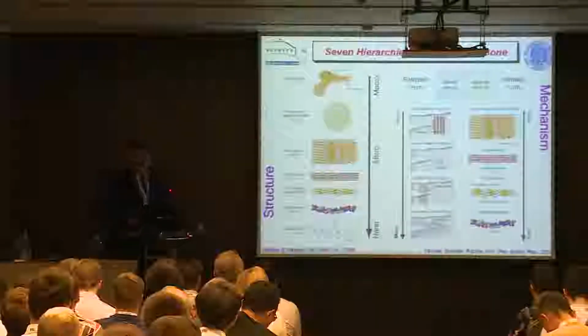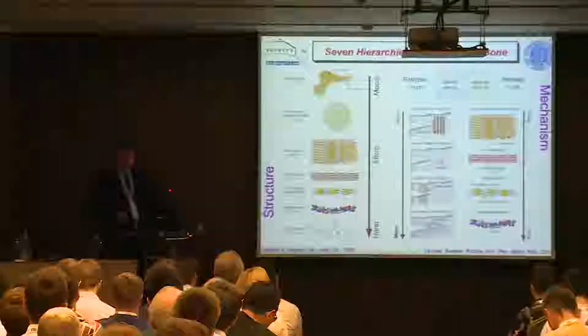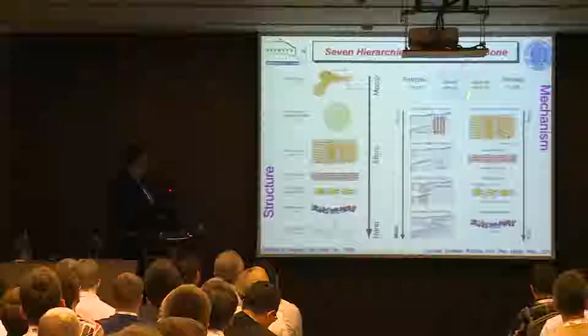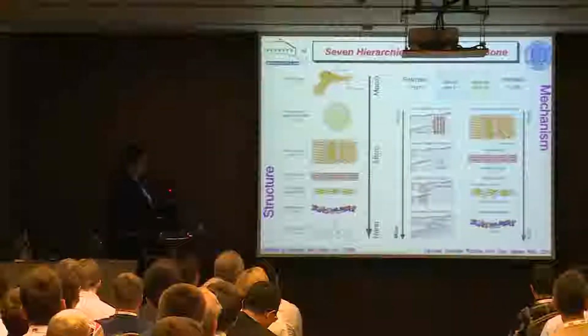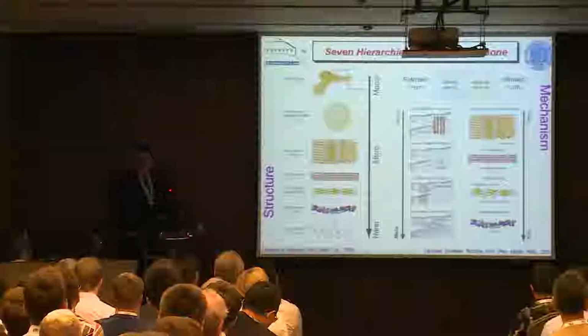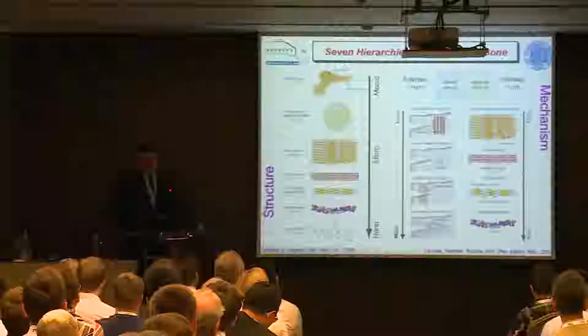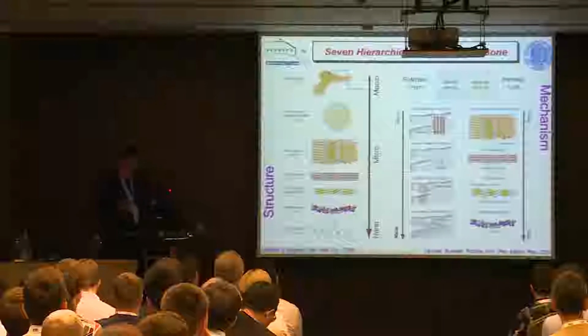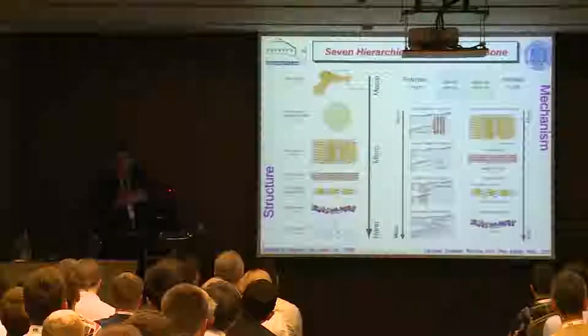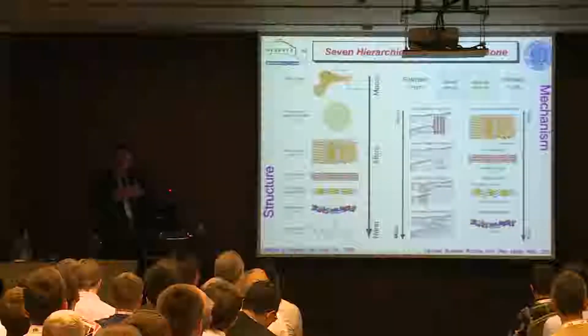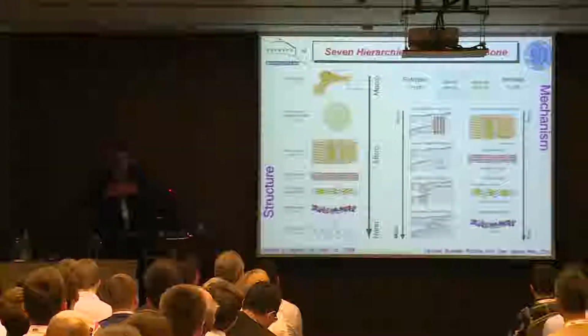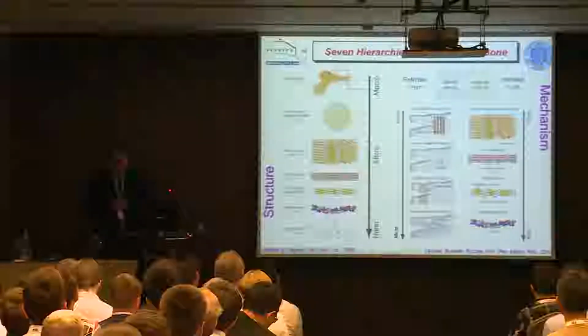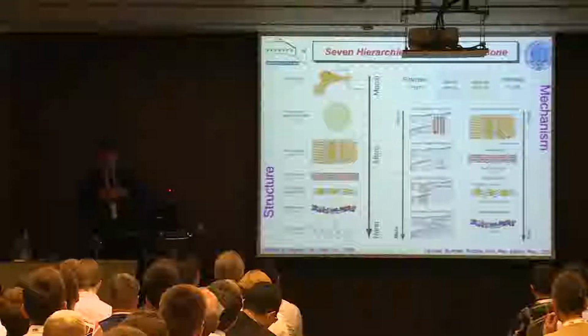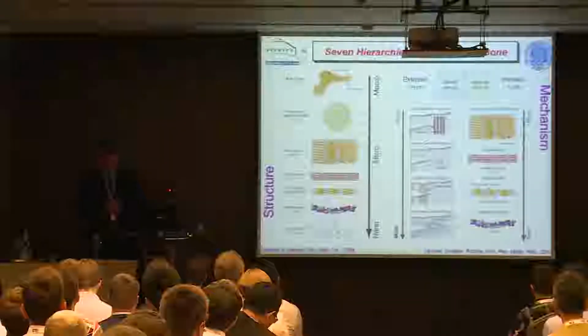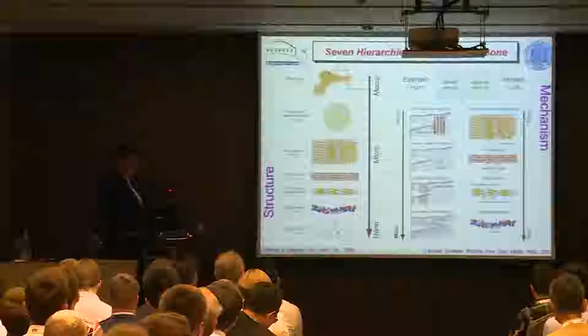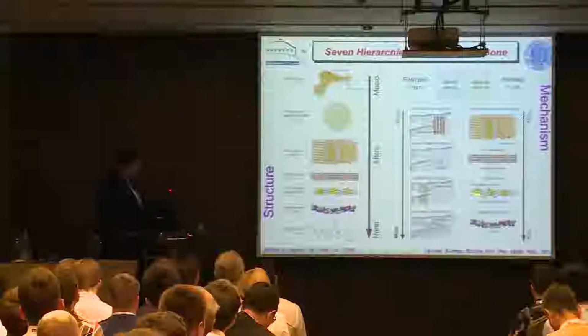Now how is bone toughened? Bone's a pretty resilient material, and this extrinsic-intrinsic notion works reasonably well. If you look at mechanisms below about a micron, we talk about this being ahead of the crack tip. It's plasticity, and plasticity in bone has a variety of mechanisms, but the principal one that is most common is the fact that you've got collagen, and the collagen simply stretches, and then it tends to slide apart, and we have something called fibrillar sliding, which is just the sliding of collagen molecules next to each other. That's a plasticity mechanism, but if anything stops that, if anything locks that up, that's how you lose ductility in bone.